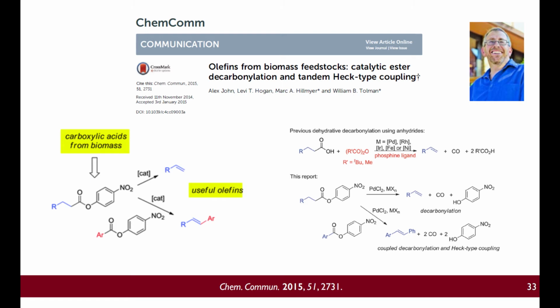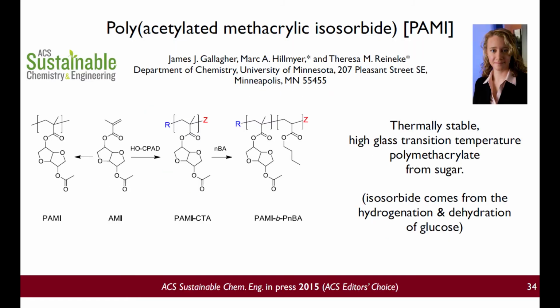And what will come out, you'll see very soon, is our work on using isosorbide as a starting material for sustainable polymers. And this is work with Teresa Reineke, where we took isosorbide, which comes from the hydrogenation and dehydration of glucose, and put an acetate on one side and a methacrylate on the other. And the great thing about this is we can polymerize with controlled radical polymerization now, and we end up making a material that has a glass transition temperature of about 130 degrees Celsius. So that hopefully will address some of these thermal limitations that can be evident in other sustainable materials.